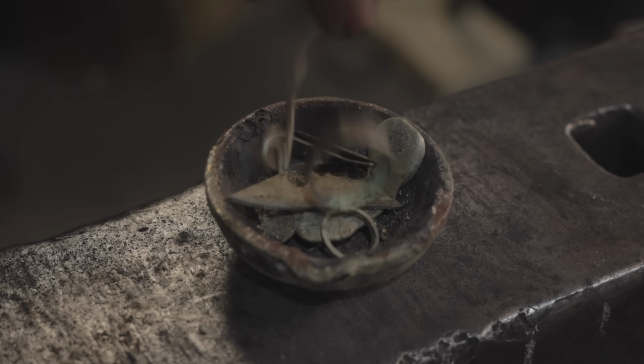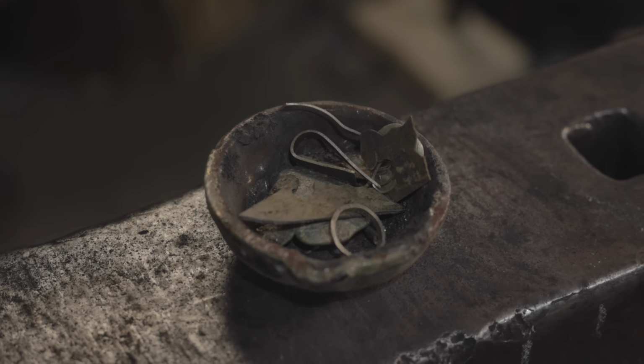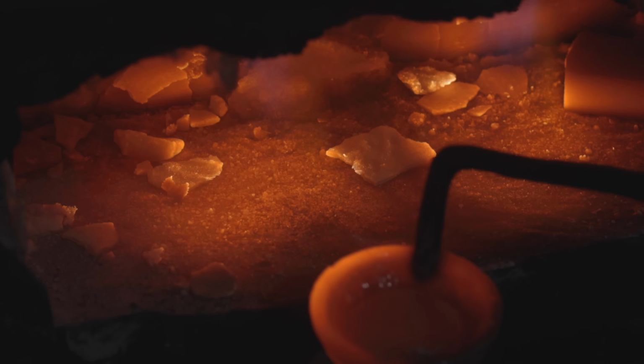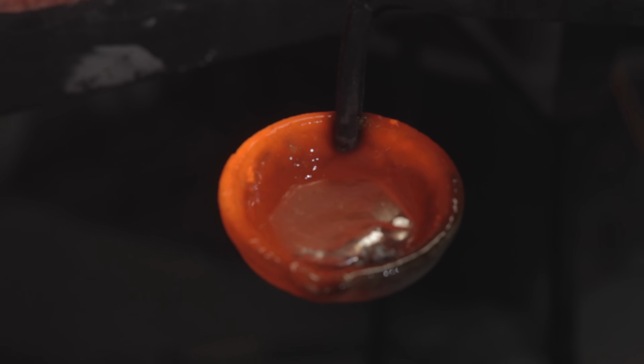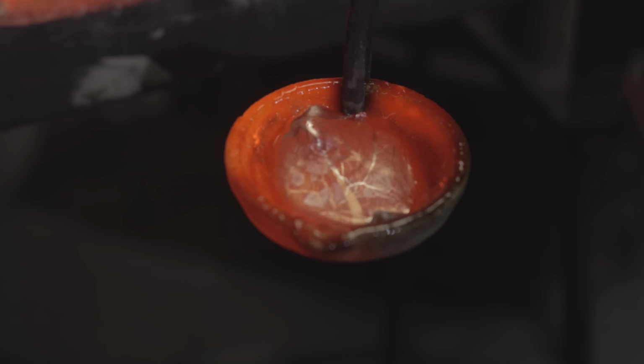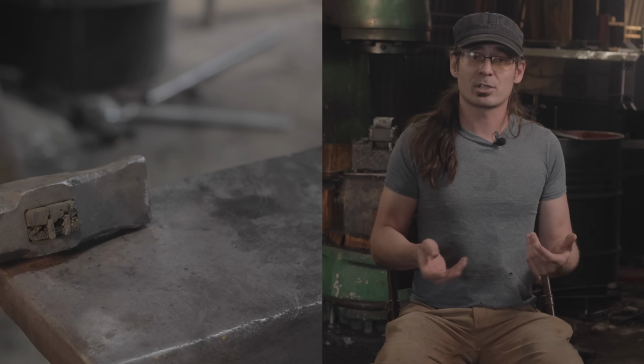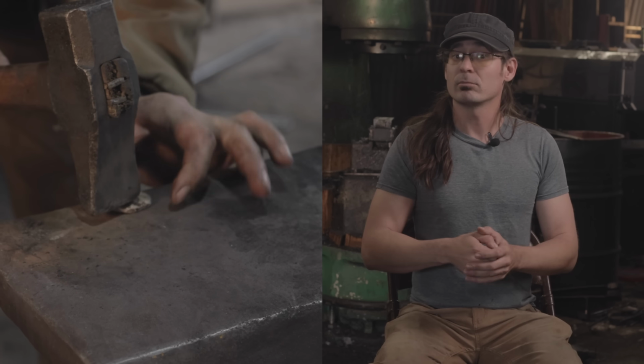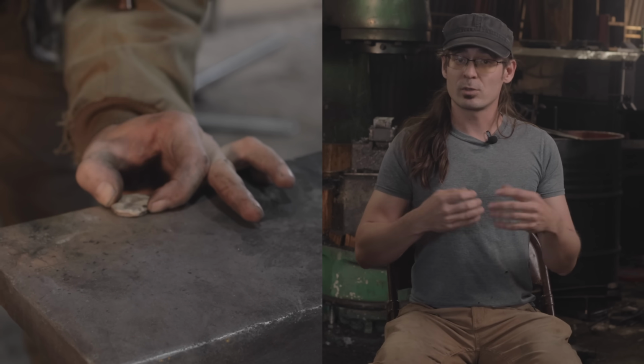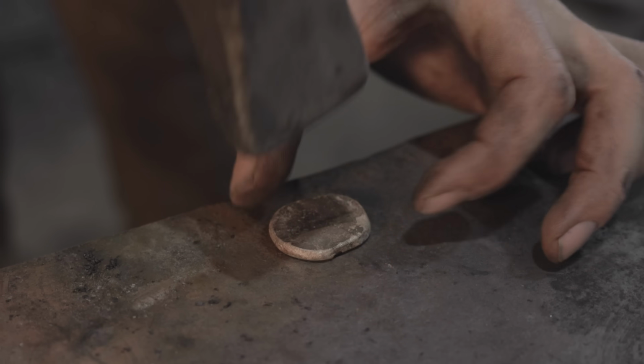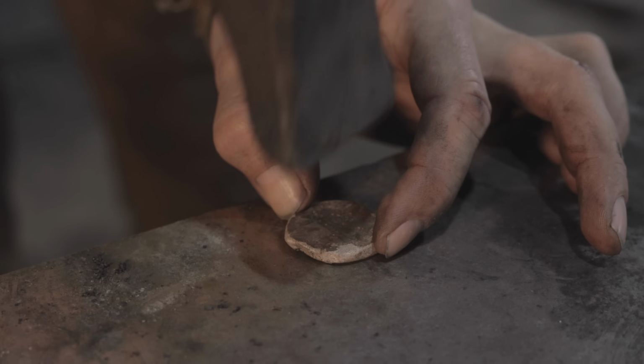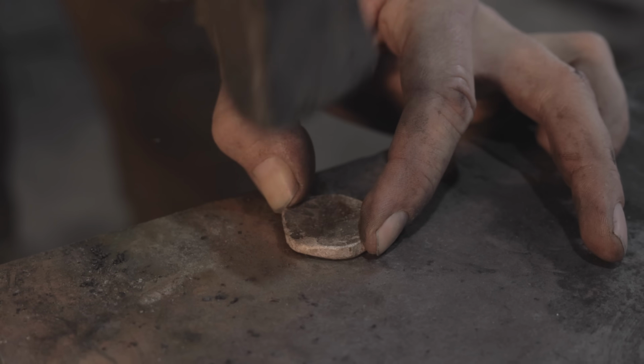So what you're supposed to do is start forging your Wootz puck at a relatively low heat until the carbidic lattice starts breaking apart and the puck starts moving more like normal steel. And that's exactly what I did for this katana. I started forging out the pucks, and as soon as they started moving, I just made bars and stacked them the way I would normal Damascus.